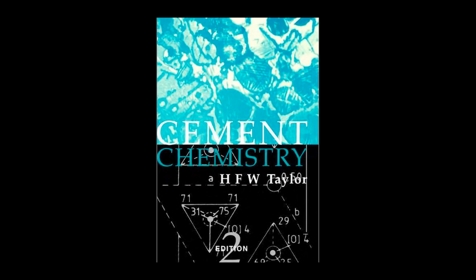How so? In these high concentration cases, the abundant calcium ions are often available to convert the highly expansive alkali silicate gel into non-expansive CSH, which effectively mitigates the worst of the damage. So a small amount of reactive material is worse than a large amount, because the small amount creates a gel with the perfect composition and distribution to swell uncontrollably. That is a powerful lesson in nonlinear chemistry.